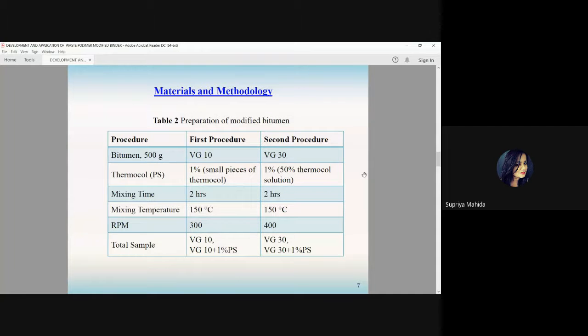Then after getting this, how can we incorporate this waste thermocol in bitumen? We have two different procedures. First, we directly use the thermocol in bitumen, and the second process turns the thermocol from solid form into liquid. The first procedure describes that we add small pieces of thermocol to 500 gram of bitumen, at a temperature of 150 degrees Celsius, and mix for 2 hours at a speed of 300 rpm to get a homogeneous mixture of thermocol modified binder.